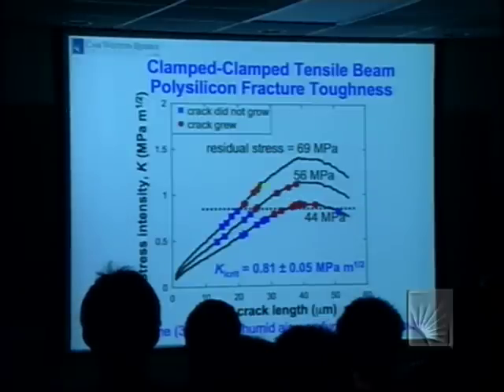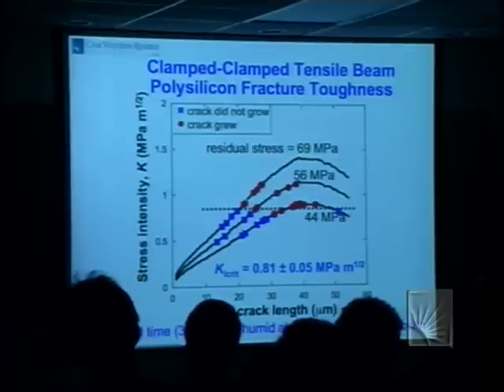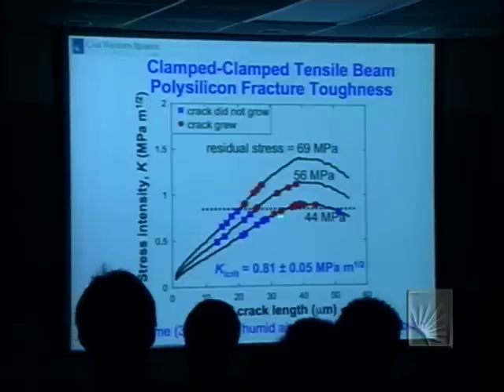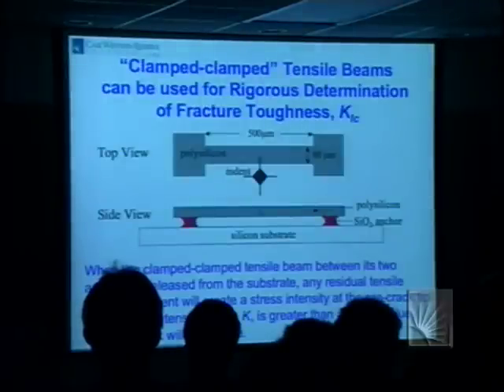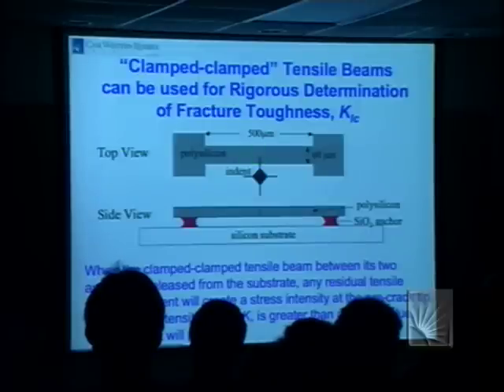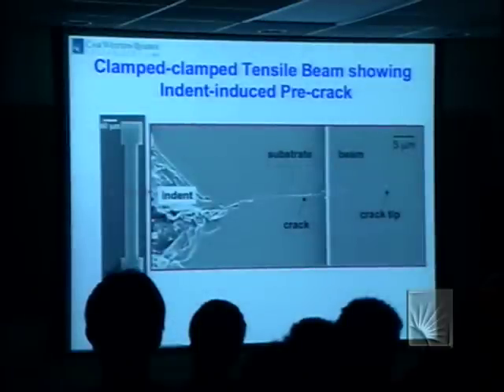These solid lines are calculated stress intensity factors for different crack lengths. The fact that they go through a maximum and then decrease just has to do with what happens to the stresses in this beam as this crack grows. That's a finite element calculation.